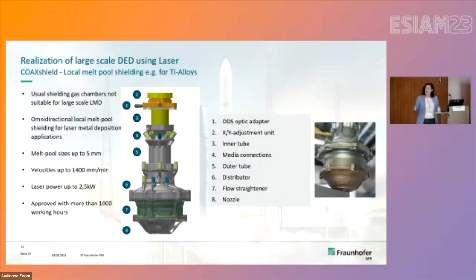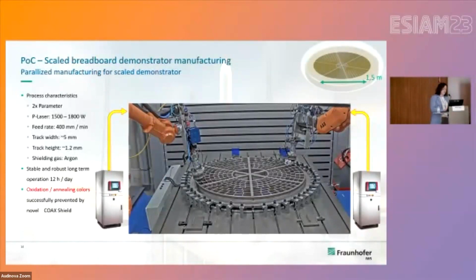So one of the nice side effects of printing such a part was the development of a new nozzle for our family, a coax nozzle with an integrated gas shielding device. You see this is a quite wide nozzle, where to avoid flooding the whole lab, we decided to create a laminar flow area directed to the substrate to get by these melt pool sizes and velocities you can see over there, a well isolated area to avoid the oxidation of the titanium parts. In the video, I can make it run for you. You can see the printing during the process with the two robots.